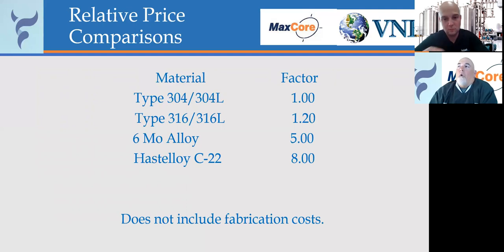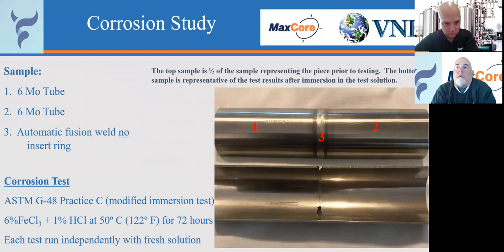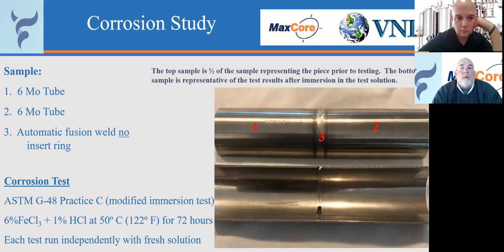So moving forward with the corrosion study, this is a sample that we did where we actually welded some 6-moly tubing to 6-moly tubing using an automatic fusion weld with no insert ring. And I'm going to talk about insert rings in just a minute. We did a corrosion test of a G48 practice C test, which was 6% ferric chloride, 1% hydrochloric acid, held at 50 degrees C for 72 hours.